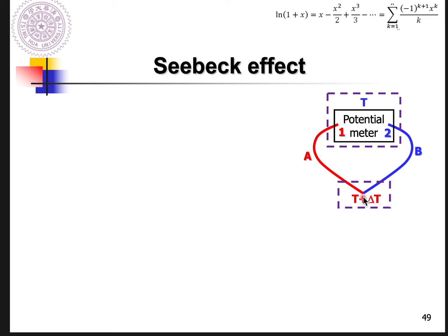So in order to demonstrate what the Seebeck coefficient is, we use these figures to explain this. If you take a look at this one, yes, there's a driving force, a temperature gradient, in this system, right? And also we have a potentiometer, implying that there's an electrical field in this system. So we do have two driving forces. So based on the flux-force relationship or equation, you can write this down, right?